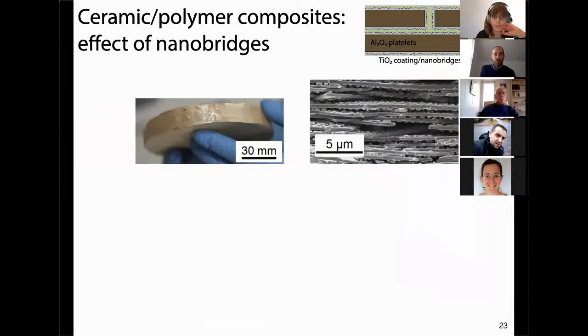And so going further, we are able to quantify this number of bridges. The only problem is that we also have many other different parameters that could play a role in the mechanical properties. The first thing would be the density, for instance. So we would need to be able to have, with the same density, different mineral bridge fractions, so that we're able to very much isolate this effect.